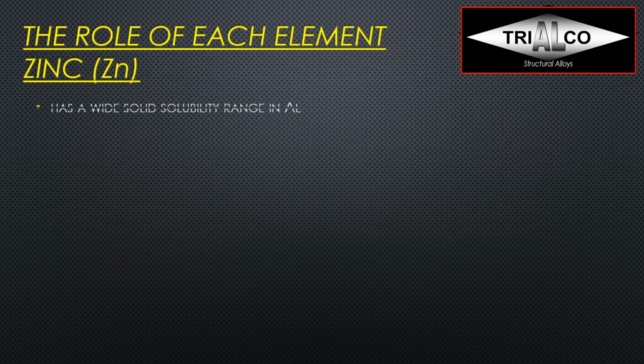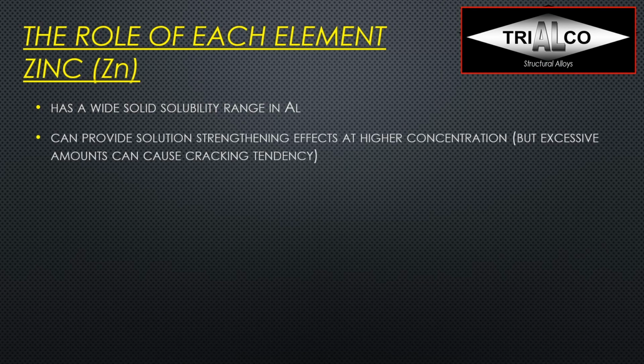Now let's have a look at zinc as an alloying element, as we can find it in the 700 series alloys. Zinc actually has a very wide solid solubility range in aluminum. It can provide solution strengthening effects at higher concentration, but excessive amounts are actually not really good and cause cracking. And we see this sometimes, for example, in an A380 alloy, where zinc is not an alloying element, but is limited to 3%.